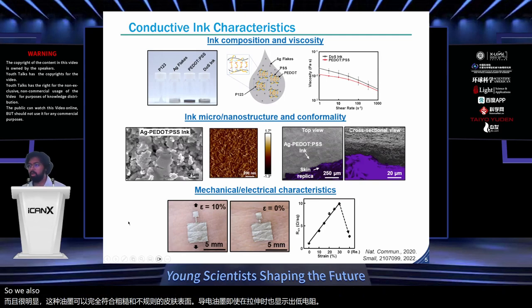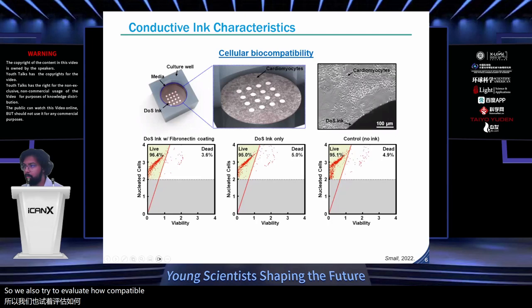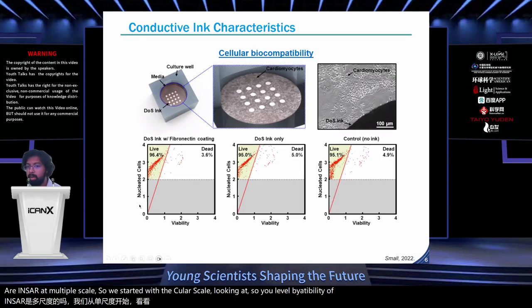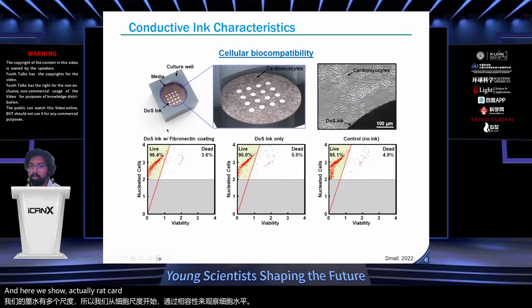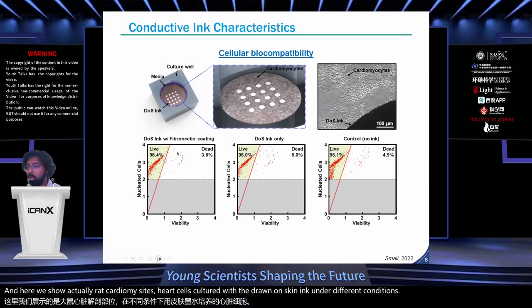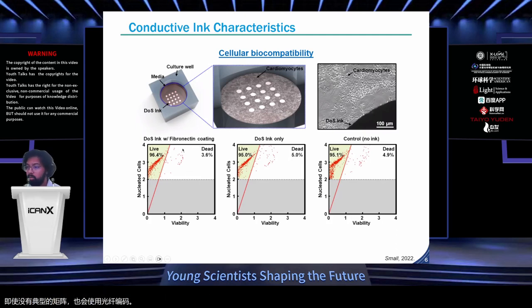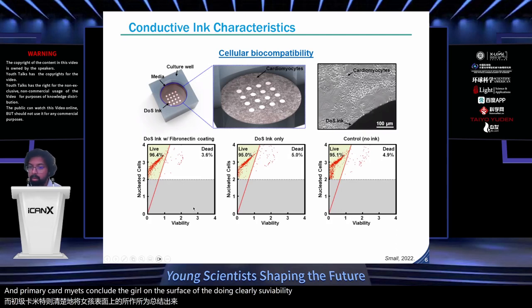We also try to evaluate how compatible our inks are at multiple scales. So we started with the cellular scale, looking at cellular level biocompatibility of the ink. Here we show rat cardiomyocytes, heart cells, cultured with drawn-on-skin ink under different conditions, even without the typical matrix fibronectin coating, and all of the conditions still show similar cell viability. Primary cardiomyocytes can clearly grow on the surface of the DOS ink. Clearly, cell viability is high. And we did a similar experiment with primary neurons as well, and they show similar results too.